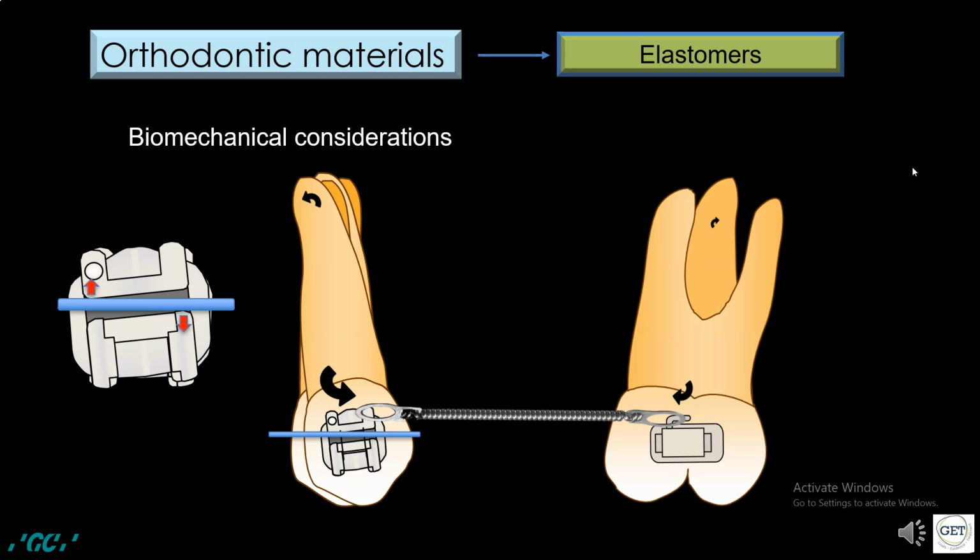If the friction is too high, a notching might occur due to the difference in stiffness between the wire material and the bracket material, leading to a deformation, a wounding of the wire. In that case, a locking is happening, and only when the wire is replaced will the problem be resolved.